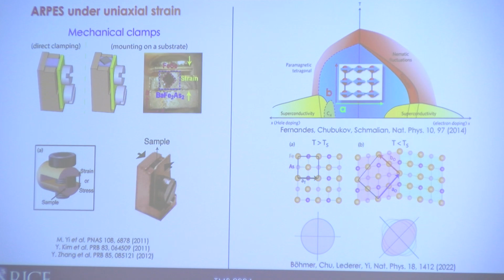but the difficulty for experiments is that when the system breaks rotational C4, part of the sample will like to break it in this way, part of the sample will like to break it that way. So what that means is that for experimental probes like ARPES and other macroscopic probes, what we measure is sort of like the overlap of these two, so you don't really get any intrinsic information about the nematic order in here. So this really drove a lot of activities across different techniques to develop these kinds of mechanical strain devices,